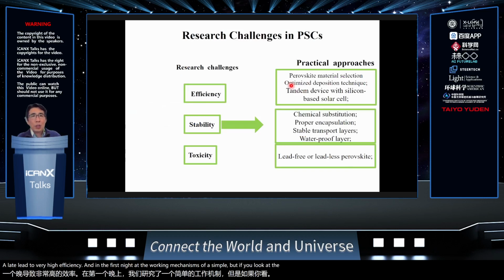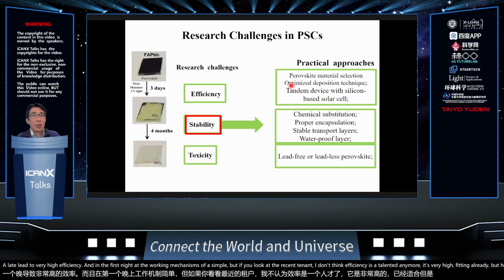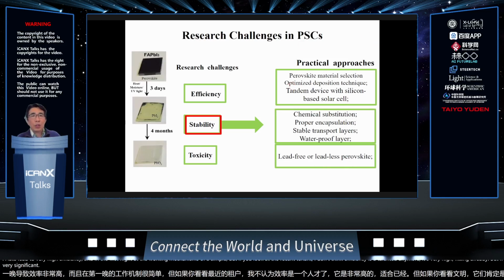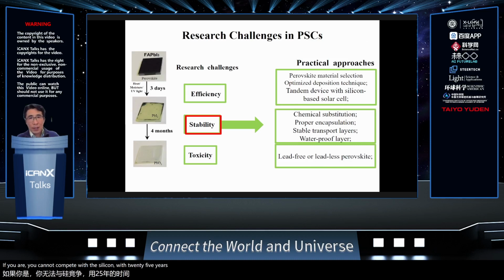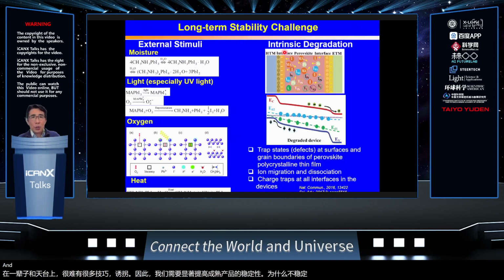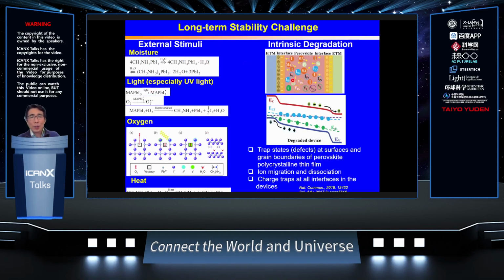But if you look at the research challenges, I don't think efficiency is a challenge anymore. It's already very high. But the stability is certainly very, very significant. You cannot compete with silicon's 25 year lifetime on the rooftop, and it's very hard to have large scale production. So we need to significantly improve the stability of the material. Why is it not stable? Intrinsically, if you look at the A, B, X sites, the bonding between these species is very weak, so there can be a lot of defects and ion migration, which will degrade the material relatively quickly.